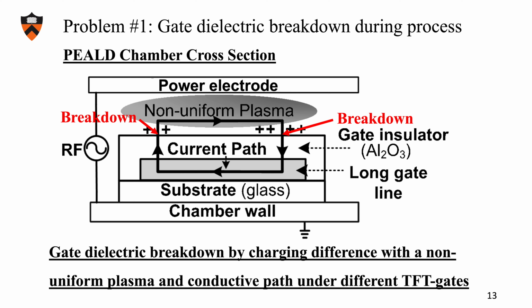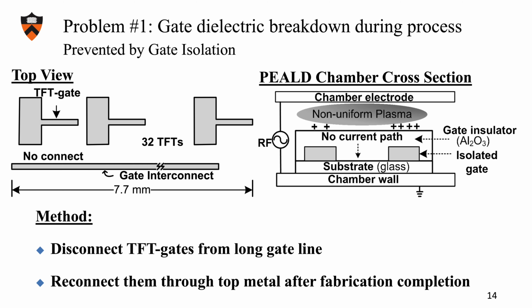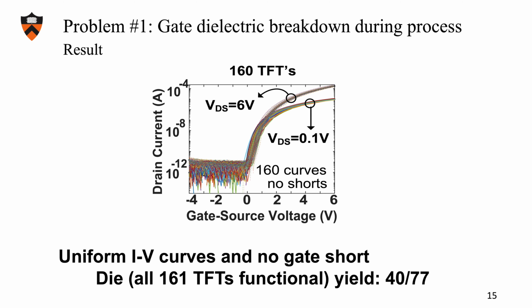To prevent this from happening, we isolated the TFT gates from the long metal traces during all of our fabrication. After the TFTs are made, we reconnected them with the top metal layer. Finally, after this, we see huge improvements in the IV curves. First, the curves are much more uniform and there is no gate short. And the number of dies with all 161 TFTs functional increases to 40 out of 77.